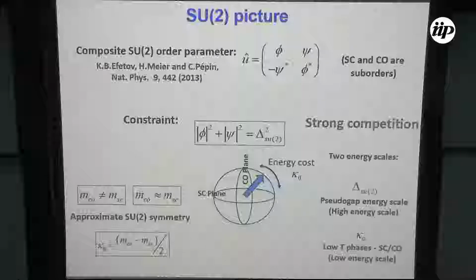So in all, we have introduced two energy scales in the problem. One is the right-hand side of the constraint, which is the SU2 energy scale, which will govern the high energy phases, the pseudogap phase. And we also have this low energy scale, this difference, which is small, which will decide the low temperature phases of the problem, which would be either superconductivity or charge order.